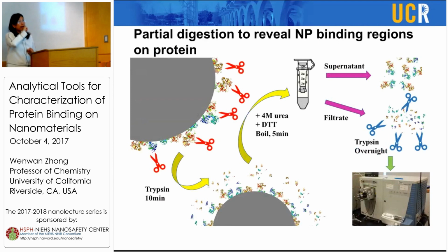But we further applied partial digestion and tried to identify the peptides that are digested in the very initial, very quick digestion round, which we believe will be the peptides affected during this conformational change, compared to the protein that remains bound, where the digestion takes a much longer time. So what we did is the partial digestion, isolate the peptides first, and then for the remaining bound protein, we continue to digest and identify them by mass spec and compare the cutting sites in both the filtrate and the protein that remains bound onto the particle.